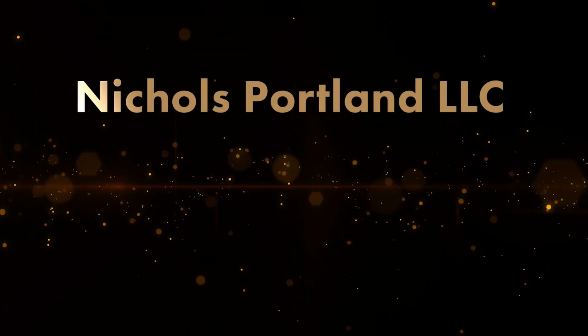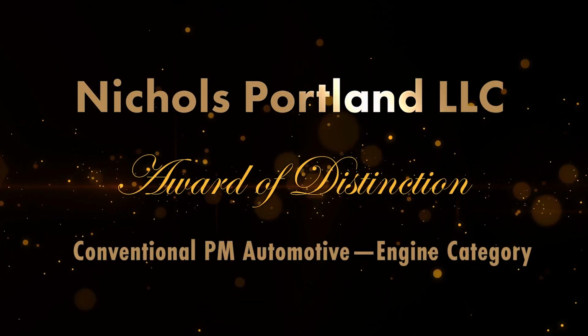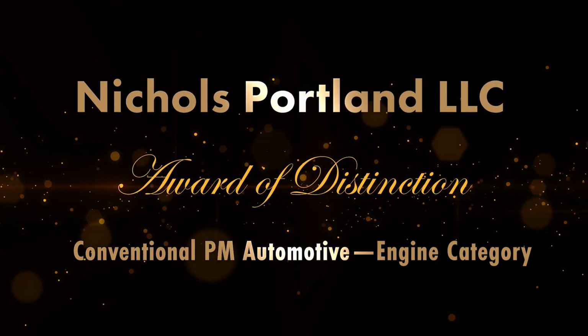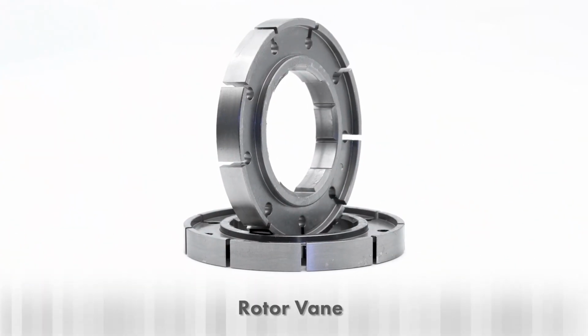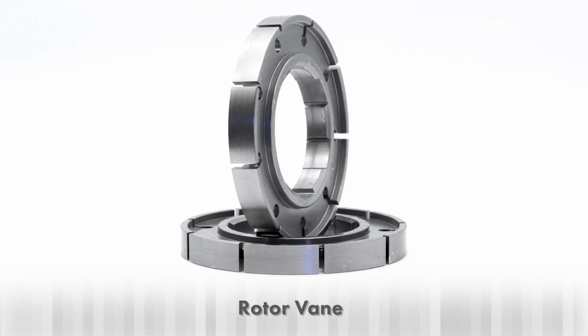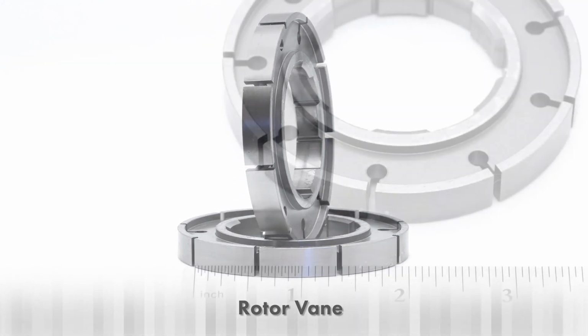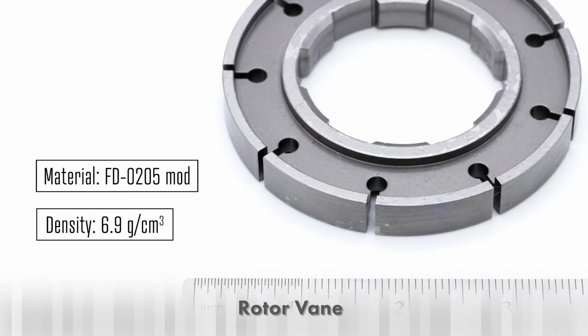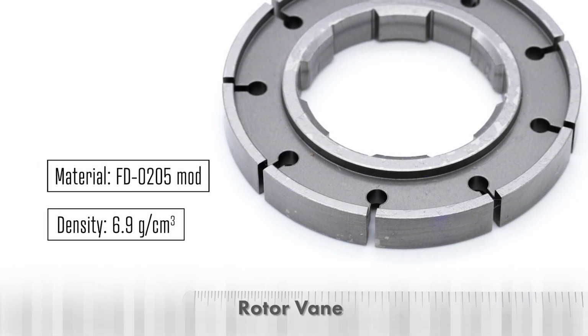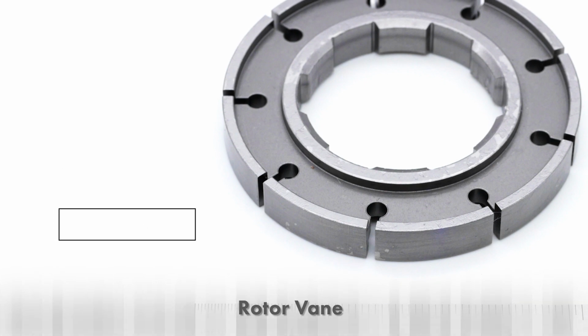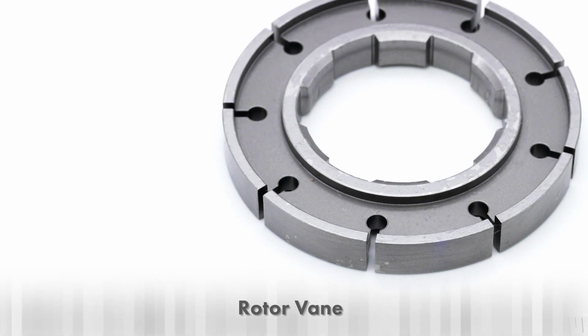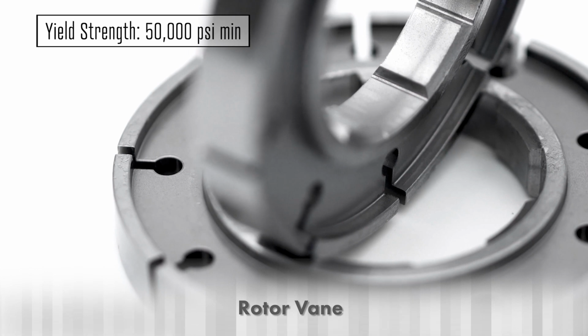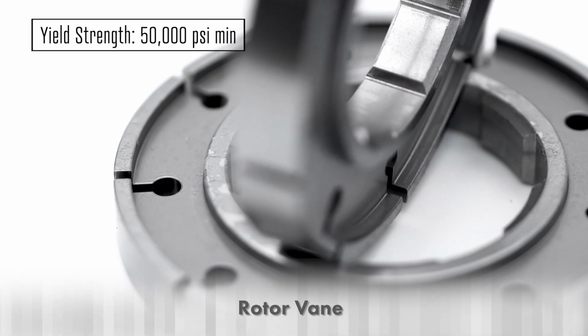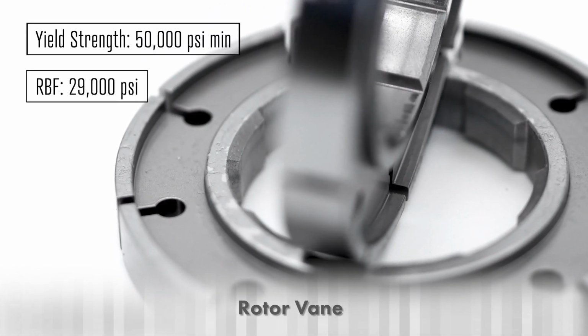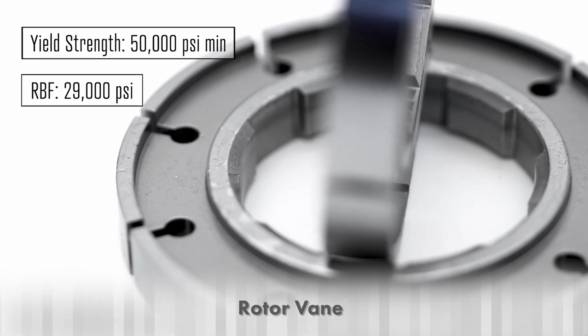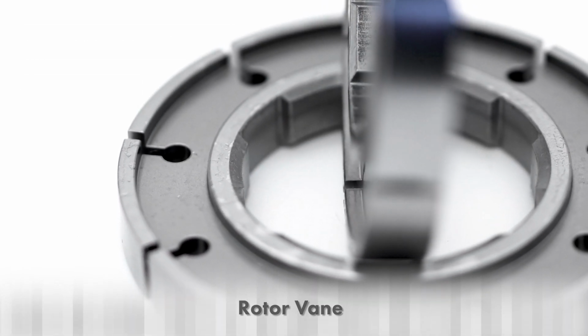Nichols Portland LLC has won an award of distinction in the Automotive Engine category for conventional PM components. This award-winning component is for a rotor vane used in an engine lubrication oil pump system, made from a modified FD0205 material to a minimum density of 6.9 grams per cubic centimeter. The part has a typical density of 6.95 grams per cubic centimeter, minimum yield strength of 50,000 psi, a 90% rotating beam fatigue limit of 29,000 psi, and apparent hardness of 76 HRB.